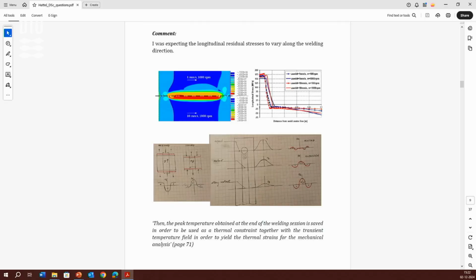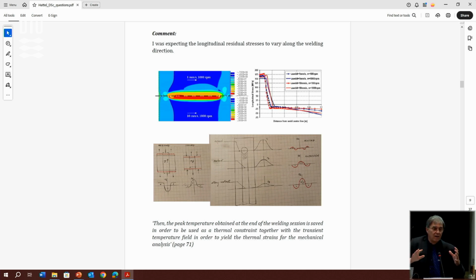Yes. So because of using the unloading, I would say in the end, when I was looking at the evolution of longitudinal residual stresses, depending on where your probe is, you have different patterns, right? Because when it's heating, you get the pattern that is typically on this side at the top. Then when it starts cooling down, and then when it's cooling further down. And when I look at this paper, it's everything the same color, so it's because it's done in the end,